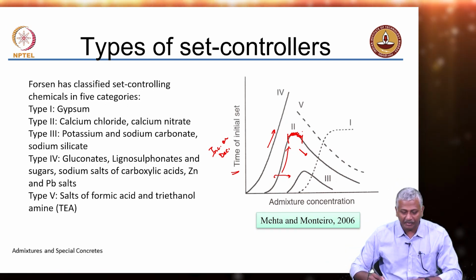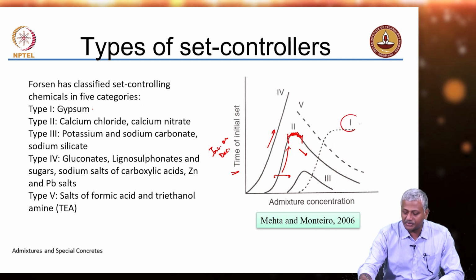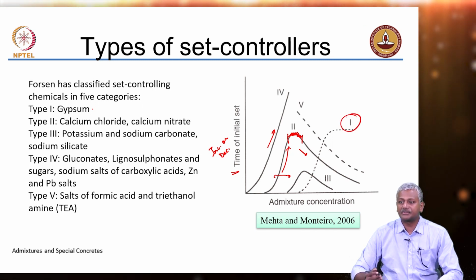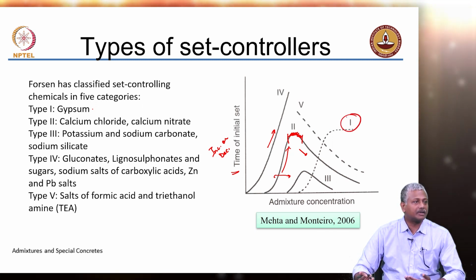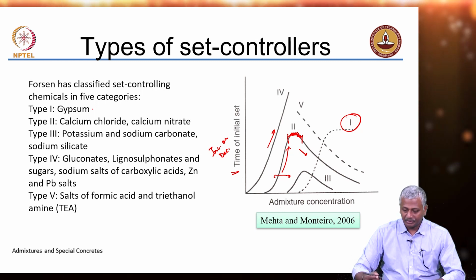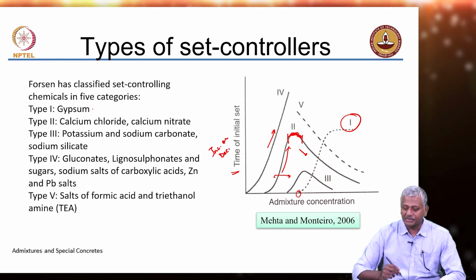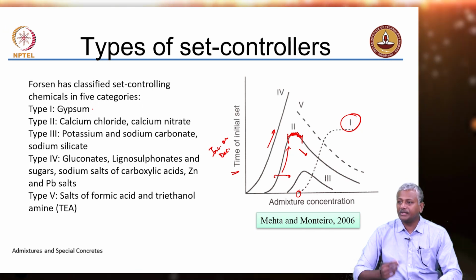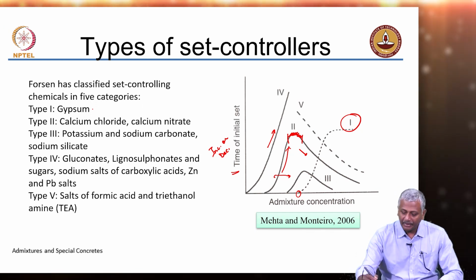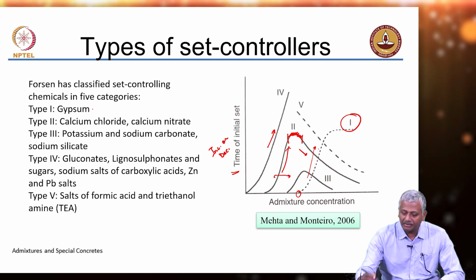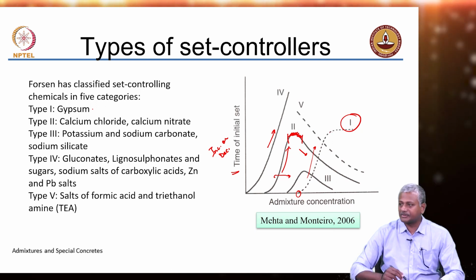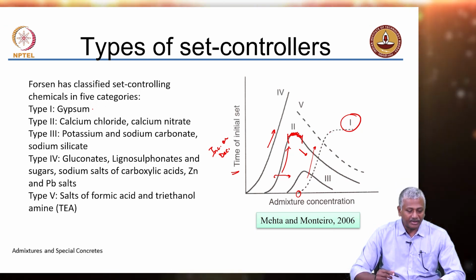So, what are these types of chemicals? If you take type 1, gypsum, which is typically used as a set controller in cement, you have certain minimum concentration that you need to add to really induce this set control, and then the time of setting increases and then more or less remains constant, it does not really increase too much beyond that.